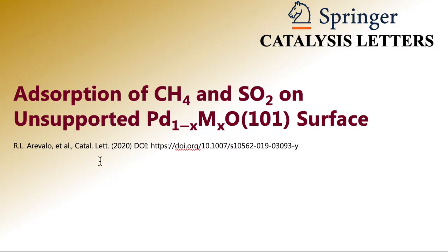So in this work that we have recently reported in Catalysis Letters, entitled "Adsorption of CH4 and SO2 on unsupported Pd1-xMxO(101) surface," we use first principles calculations based on dispersion-corrected density functional theory, or DFT-D3, to systematically screen the metal impurities M, where M is a transition metal, on a palladium oxide 101 surface to identify the Pd1-x